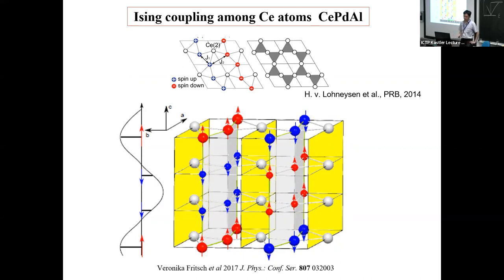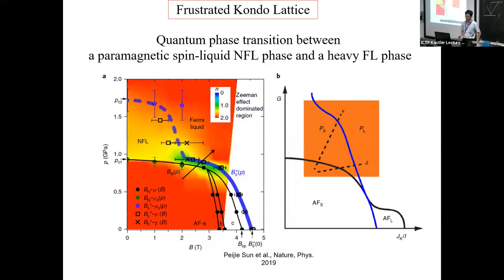But this long range order could be easily suppressed by applying field or pressure, and that's how they observe this paramagnetic phase. This is a global phase diagram of this material in terms of pressure and field. As you can see, between this antiferromagnetic long range order phase and the heavy Fermi liquid, there exists this finite size window over which we can see non-Fermi liquid behavior. So this is not a point, but a phase. The green and yellowish regions are all this strange metal phase. Experimentally, you can tune the field or pressure along this arrow direction so that you cross a finite range where you see this non-Fermi liquid phase.